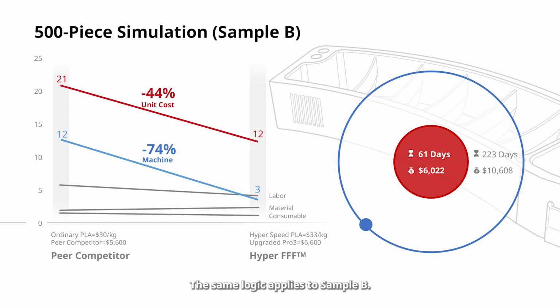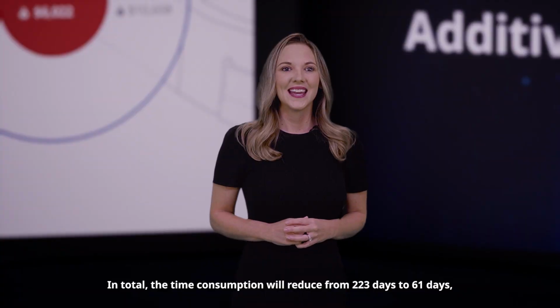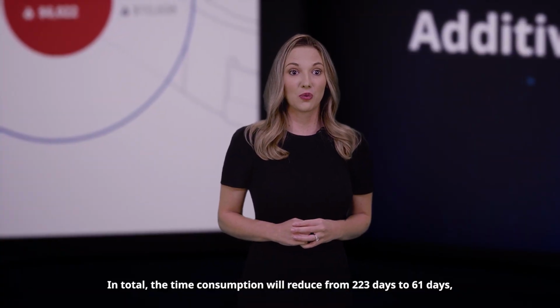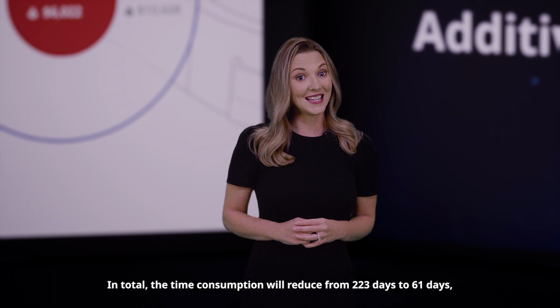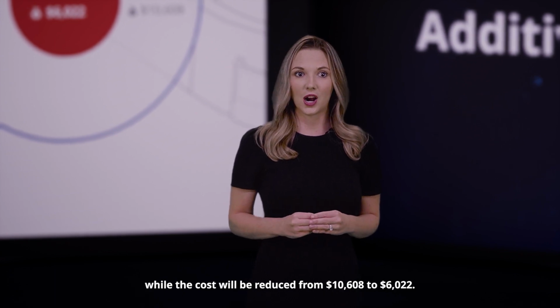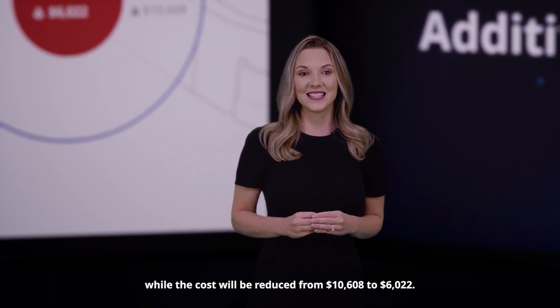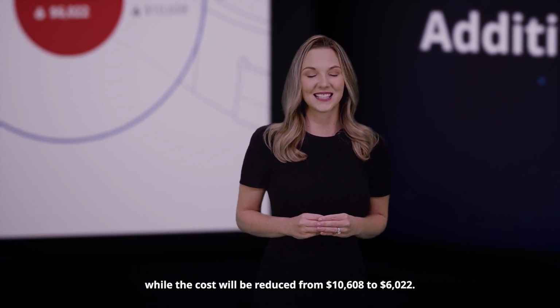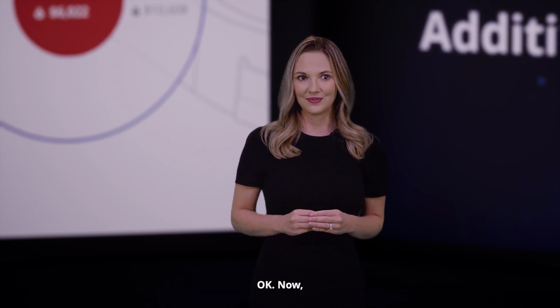The same logic applies to sample B. Machine depreciation per unit is reduced from about $12 to around $3, which is a 74% drop. As a result, the unit cost drops around 44%, from around $21 to $12. In total, the time consumption will reduce from 223 days to 61 days, while the cost will be reduced from $10,608 to $6,022.